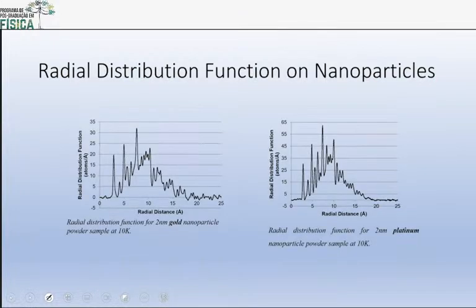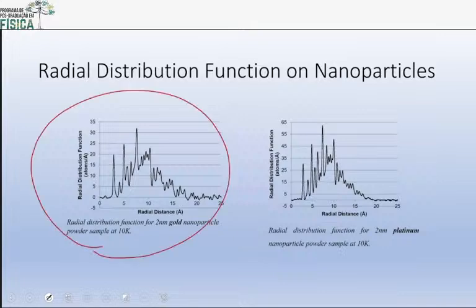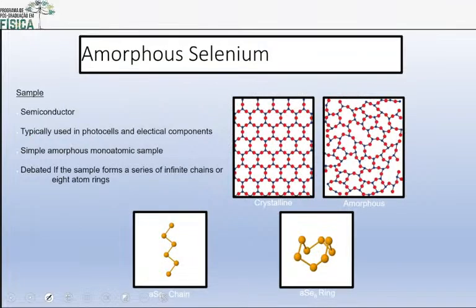So now we can look at nanoparticles. These are the nanoparticles that I said in the very beginning, gold nanoparticles that I said we wouldn't be able to use diffraction on, and here we actually measured them, and we can see their structure. Hey, look, this is a platinum, and you can see that dinner fork that I was talking about. See that? Big, small, small, small, big. It's a little distorted because it's a nanoparticle, but we can see that the nanoparticle is very small, but it's face-centered cubic. Ta-da. Just by looking at that dinner fork, someone who knows what they're doing can say, oh, that's face-centered cubic. Amorphous selenium.